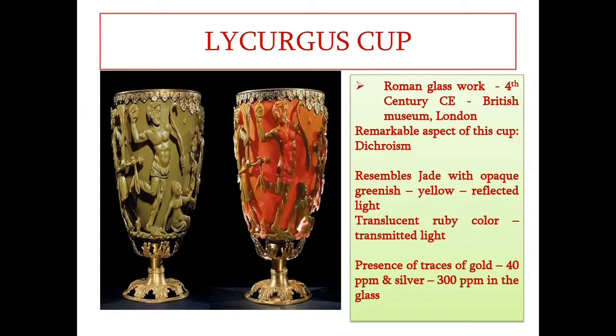When you look at the cup from outside, it resembles jade with an opaque greenish yellow because of the reflected light. But when you light this cup from the inside, the cup glows with a transparent red ruby color, which is because of the transmitted light. The X-ray analysis and chemical analysis done on this reveal traces of gold, 40 parts per million, and silver, 300 ppm, in the glass.